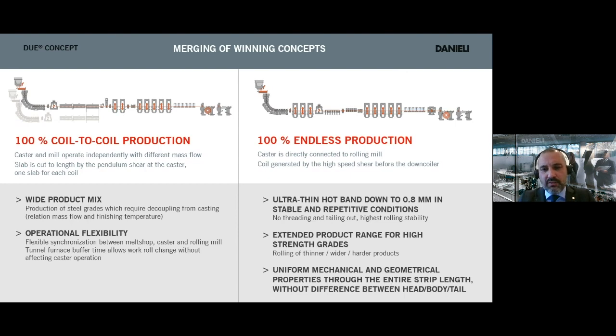On the other side, what is now becoming a quite mature technology is the pure endless production, where caster and mill are connected to each other, so they are using the same mass flow, and the coils are cut to length by the high-speed shear at the entry side of the downcoiler area. Typical products for endless are thin and ultra thin gauges, which can be made in a stable and repetitive condition, since there are no more threading or tailing outs.